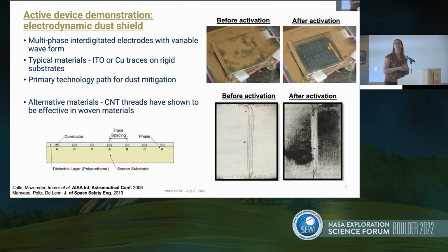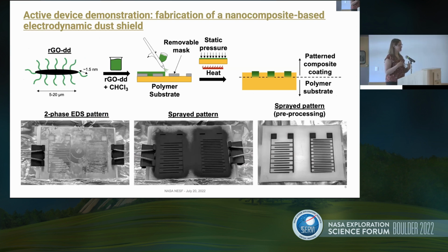into those flexible substrates. So there's one really great example already published in the literature where they used carbon nanotube threads woven into spacesuit materials as interdigitated electrodes. And you can see in the bottom images that it was effective at clearing dust from the surfaces. So that's very encouraging. So how do we do this with our substrates?